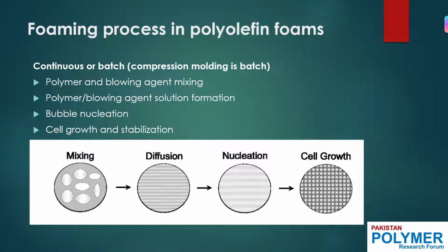So if I divide it into different steps, first of all, polymer and blowing agents are required to be mixed. And then polymer blowing agent solution formation, where you will have to study the rheological properties. And then the bubble nucleation, which means the start of bubbles. And the last step is the cell growth and the stabilization. So you can have a look at the picture below, which explains the whole process: mixing, diffusion, nucleation, and cell growth.